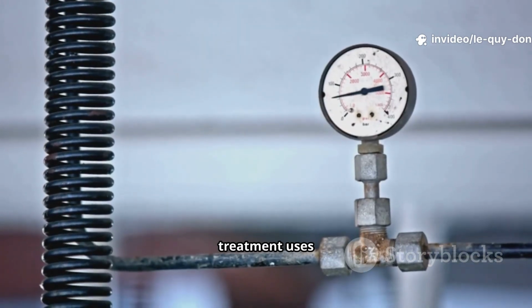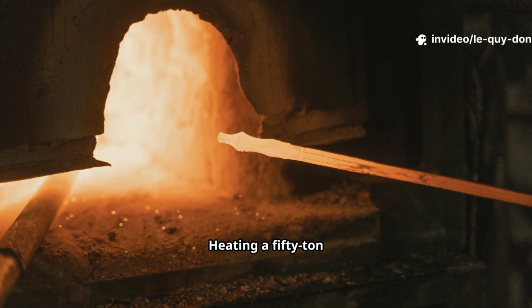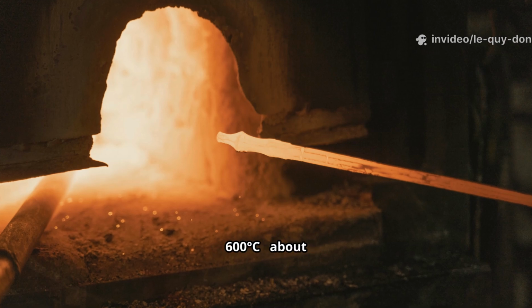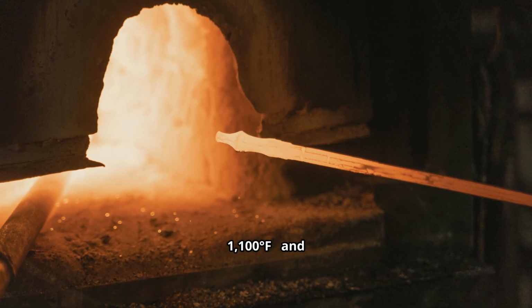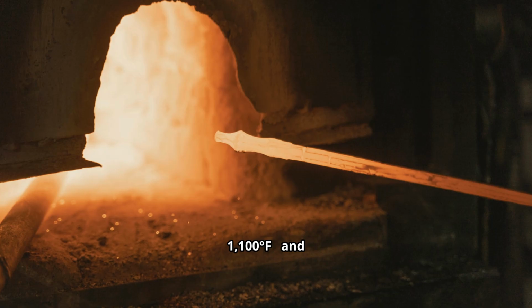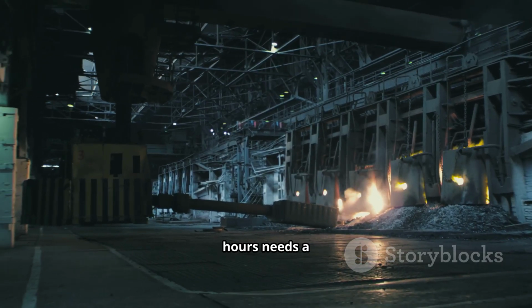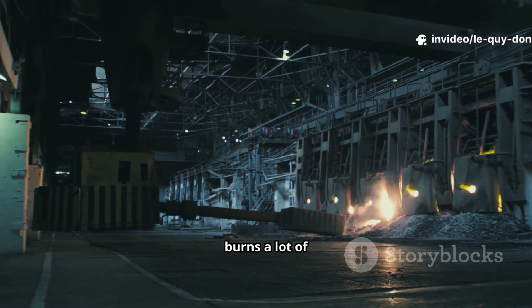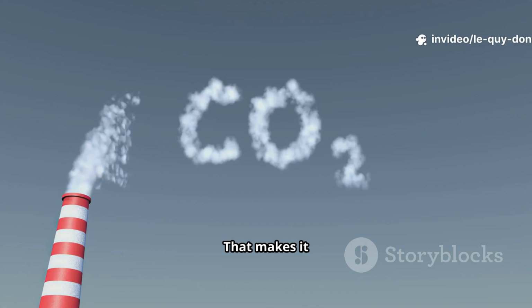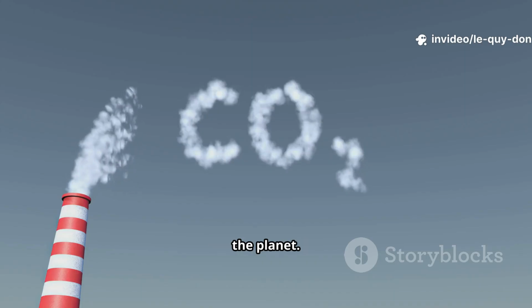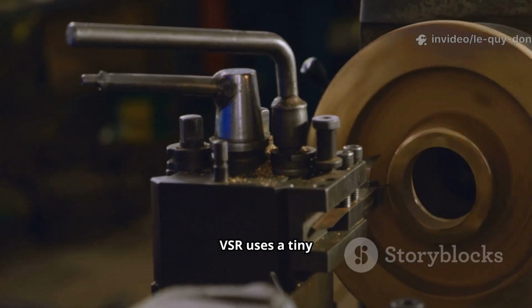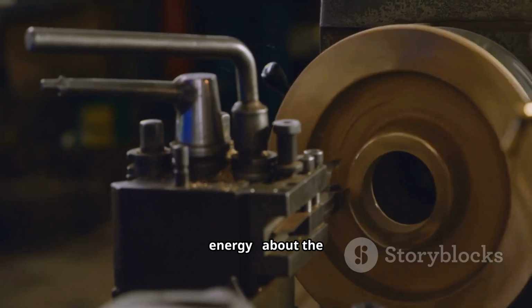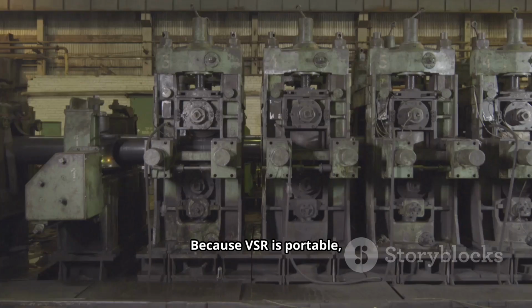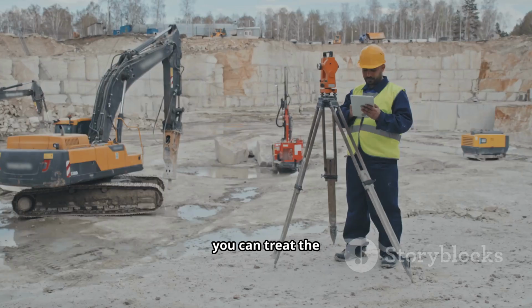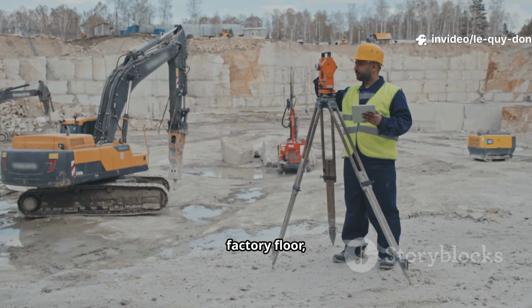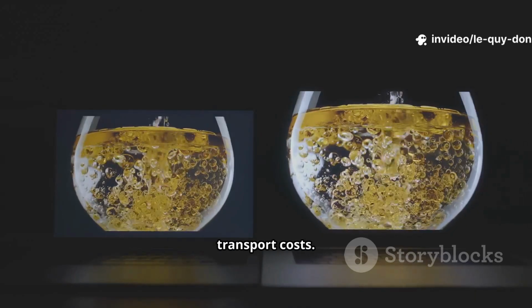First, heat treatment uses enormous energy. Heating a 50-ton structure to over 600 degrees Celsius, about 1,100 degrees Fahrenheit, and keeping it there for hours needs a massive furnace and burns a lot of fossil fuels. That makes it costly and bad for the planet. VSR uses a tiny fraction of that energy, about the same as a household appliance. Because VSR is portable, you can treat the structure on the factory floor, saving time and transport costs.